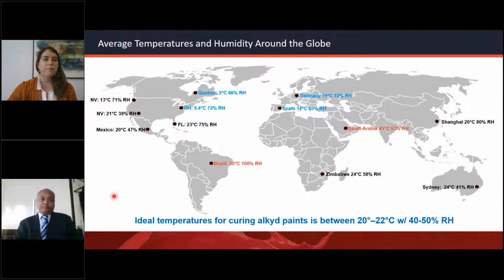A major issue with alkyd coatings globally is that they are greatly affected by temperature and humidity. If you have a change in humidity above or below the standard 40 to 50%, or a change in temperature above or below standard scientific room temperature of 20 to 22°C, you can have significant impacts on your drying time.